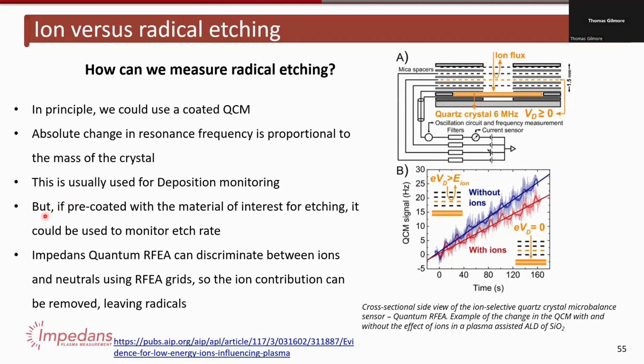But what would happen if you pre-coated the quartz crystal microbalance with the material you're interested in etching? Then you can monitor the frequency change in reverse. So you could be using it to monitor etch rate. Now, obviously, if you place this on a substrate, you have ions present, right? So we do have a sensor called the quantum RFEA, and this is built like this. It has a quartz crystal microbalance on the bottom, and it has the RFEA grids above it. So you can repel the ions or let them through. So we think in this case, if you repel the ions and monitor the resulting deposition rates, or I suppose etch rates, that could be a way of live monitoring what the radicals are doing.